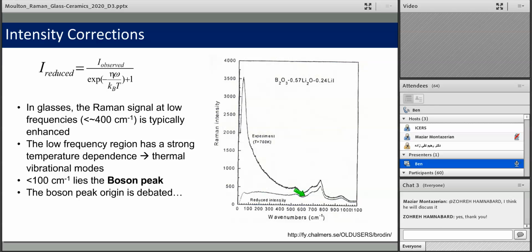But the problem is that at low frequencies, you see this peak. It may not be just coming from the vibrational population, but it's coming from actually a feature called the boson peak. And so other temperature corrections actually eliminate this boson peak, and there's some other peaks under here, not readily seen in this spectra, that were eliminated. And so one thing, if you get to reducing your spectra by more than a simple intensity correction, such as I presented, you'll end up eliminating these peaks and eliminate information from your spectra. And this to me is a loss of an opportunity. So I just use a simple reduced intensity.